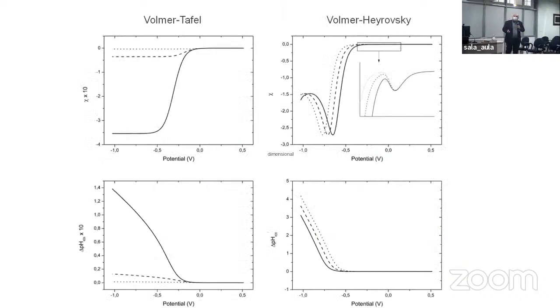It also depends on the different materials, because the mechanism of hydrogen formation changes. Both are Volmer-Tafel or Volmer-Heyrovsky. In the case of Volmer-Heyrovsky, the pH change is much more important than in the case of Volmer-Tafel. The difference is that you have the high mobility of hydrogen atoms over the surface. And in the case that we don't have the high mobility, we have an important interfacial pH change.